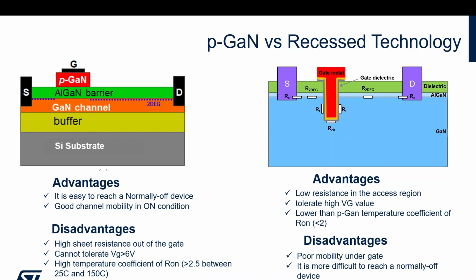Okay, let's concentrate on the power. On the power, basically, one of the problems that you have with the nice structure that I was describing before is that the structure is typically normally on. So you need a negative voltage in order to turn it off. So if you want instead to have something which is normally off, like is required in many of the power applications, or some of them at least, you have two possibilities. One is to undergo the pain of growing also P-type, so you make junctions that control the gate and eliminate the 2D gas at gate voltage equal to 0, so that you can have a normally off device. Or you go through a recess in which you basically have an amp and you combine this with a MOSFET. Each one of them has advantages and disadvantages that we can name.